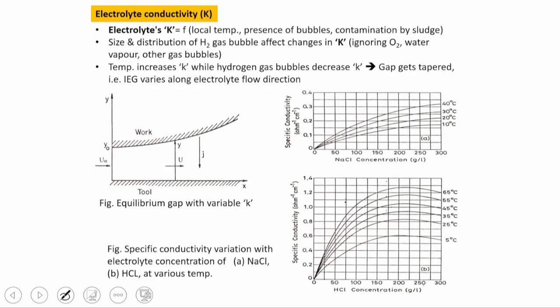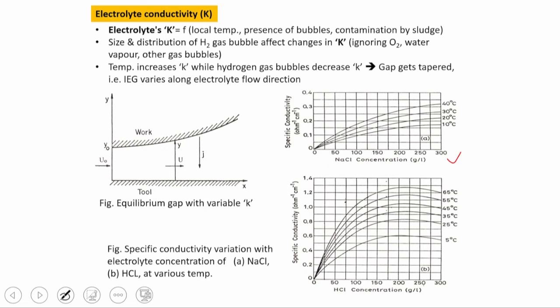So now the electrical conductivity of this electrolyte actually increases because of the rise in temperature. When temperature rises, the electrical conductivity of the electrolyte also increases. Suppose we consider this NaCl solution, if we increase the temperature from 10 degree to 20 degree, you can see the specific conductivity, the electrical conductivity of this electrolyte, increases. From 10 to 20 degree, 20 to 30 degree and 30 to 40 degree, you can see electrical conductivity increases. Also if we increase the initial concentration, the electrical conductivity also increases.